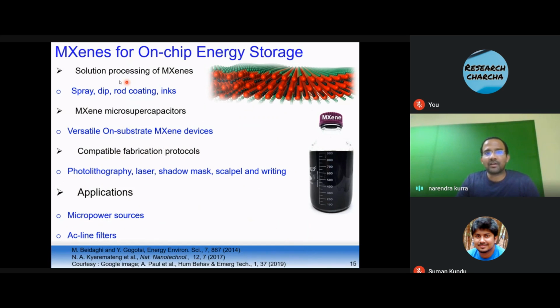And further, I moved on to MXenes. MXenes are layered materials. As shown here, this is a well-known example, titanium carbide MXene. You can see here 3 layers of the red ones are titaniums, 3 layers of titanium with sandwiched carbon layers, 2 layers of carbon, and this represents the surface functional groups.